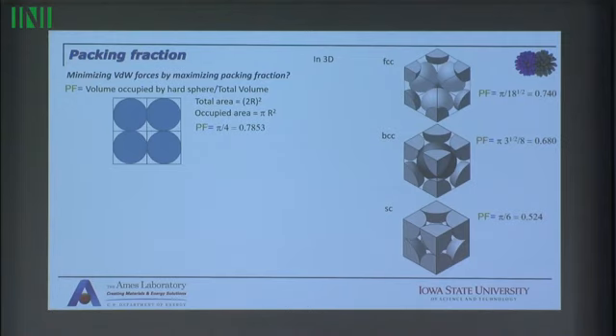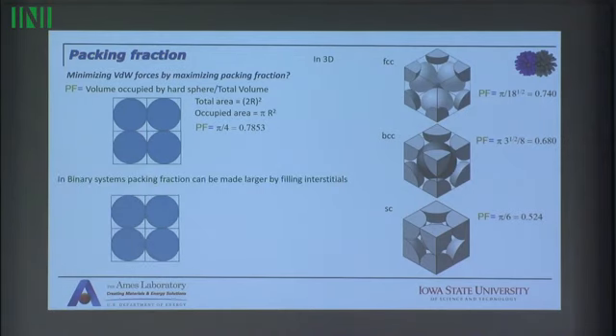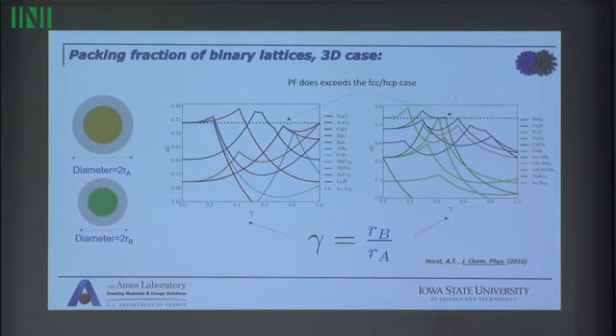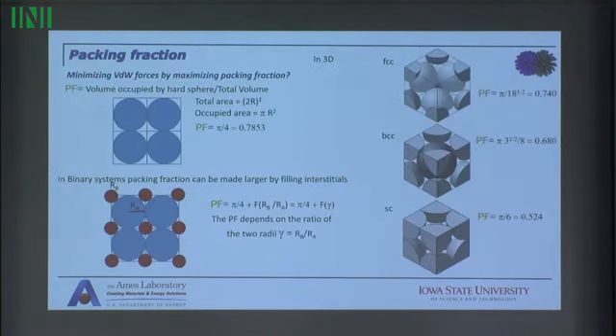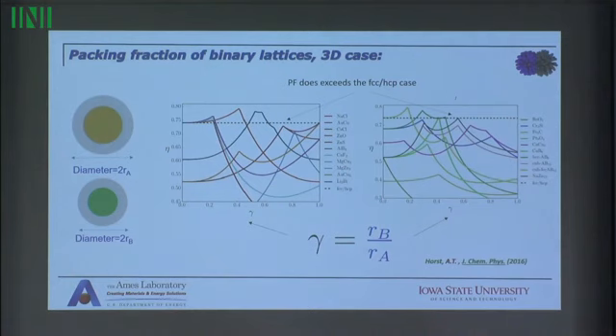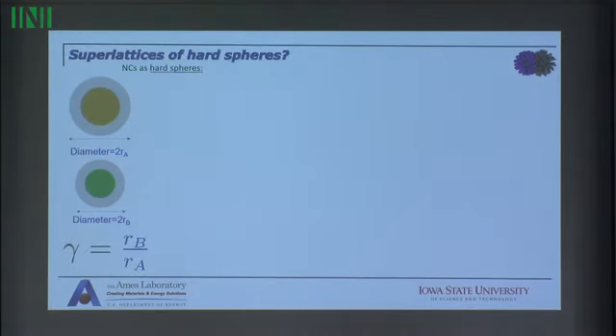But the thing is, here we are considering binary systems. And one thing that we can clearly tell is that with binary systems, you can be more effective in terms of packing because you can always imagine that you put smaller spheres in the interstitials and in this way enhance the packing. In fact, the packing will be a function of the ratio between the big and the small spheres, which is a value that we call gamma. In general, depending on the ratio gamma, you will have a maximum packing that will depend on it. So when you go to 3 dimensions, this is what you get. These are different binary lattice structures that you can have. And you can see here that there are many cases where you overcome the maximum packing fraction of FCC, or the maximum packing fraction of any single component lattice. Why is this relevant? Well, because in an experiment, what you can do is put these things in a 2-dimensional lattice.